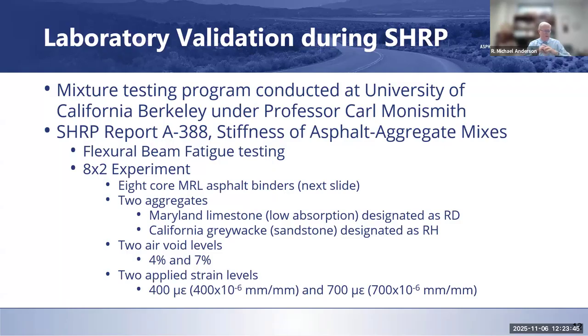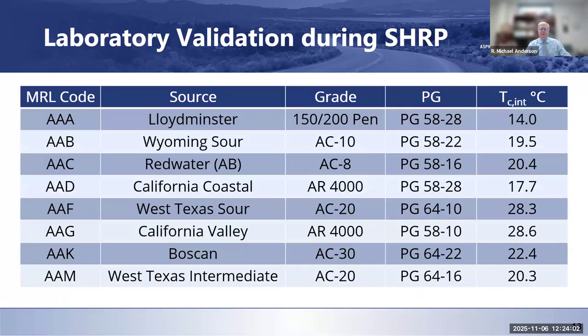The other one was a California graywacke, which was a sandstone, and they were designated as RD and RH, if that matters to you. 2 different air void levels, 4% and 7%, and 2 different applied strain levels, 400 microstrain and 700 microstrain. To get beam fatigue, those specimens were compacted using rolling wheel compaction in the lab. And then they cut the slabs out and proceeded to test them.